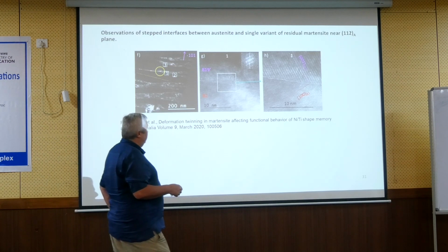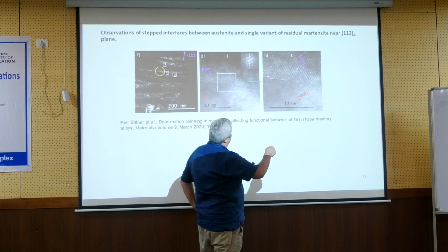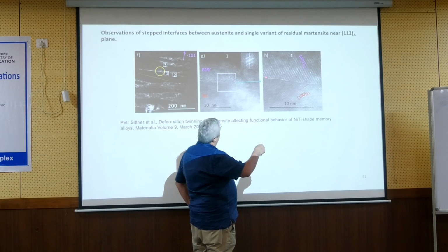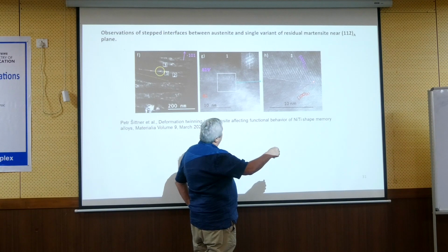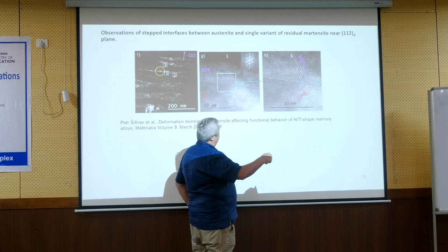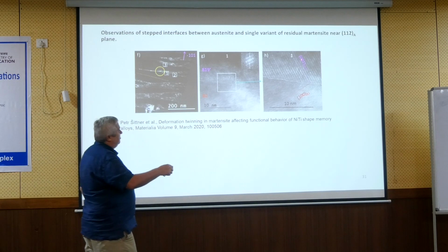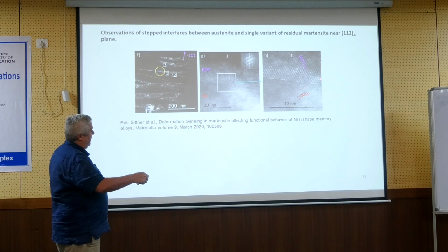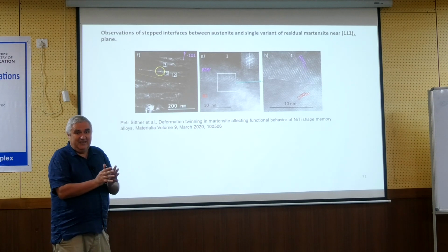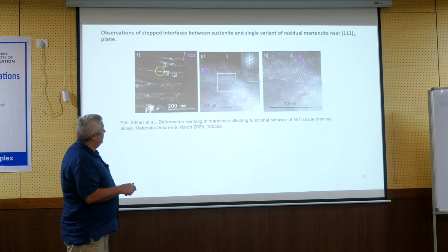One thing is interesting: if we look at these interfaces at high resolution, this is the interface, this is the 100 in B2, and this is the 001 in martensite, and you find some kind of mirror symmetry. The 100 is not parallel to the 001 because you have only one. But still there is this mirror symmetry, and we will find it repeating many times. So this is sort of evidence that when nature created this interface, strain compatibility was the key rule which had to be respected.